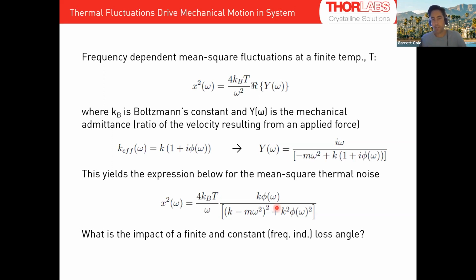I'm not an electrical engineer, but for those of you who may be, this is the same physics as Johnson noise in a resistor. So an object that has a finite resistance will have a finite electrical noise. This is the mechanical analog of that, if you want to look at it that way. So in this expression at the bottom, again, you have energy scaled with the radial frequency. And then you have this phi, which is the elastic loss. This is the imaginary component of the Young's modulus.